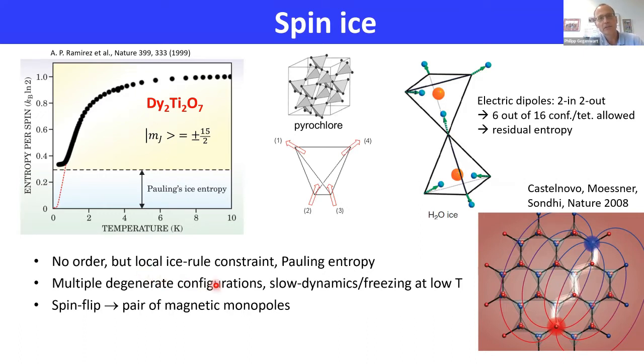And there is a residual entropy due to these multiple degenerate configurations, which is clearly visible in the experiments where entropy was calculated from the specific heat by just integration. And characteristic for these spin ices is that once you cool them down to very low energies, there is slow dynamics and freezing, and time scales are getting extremely long.